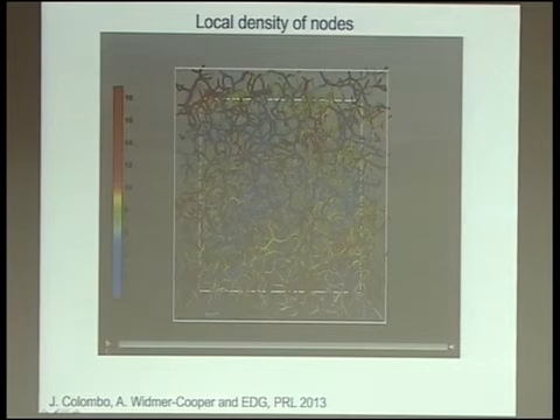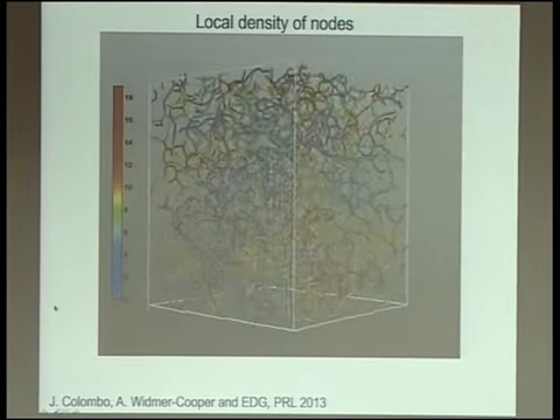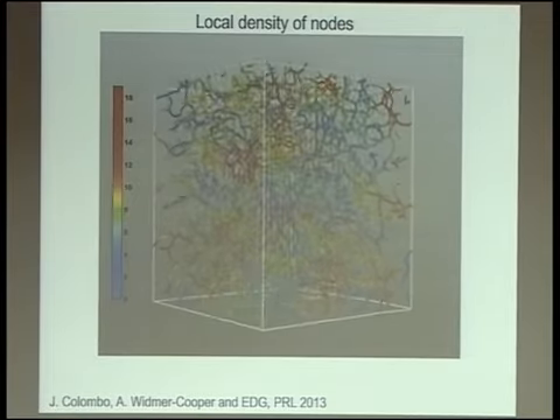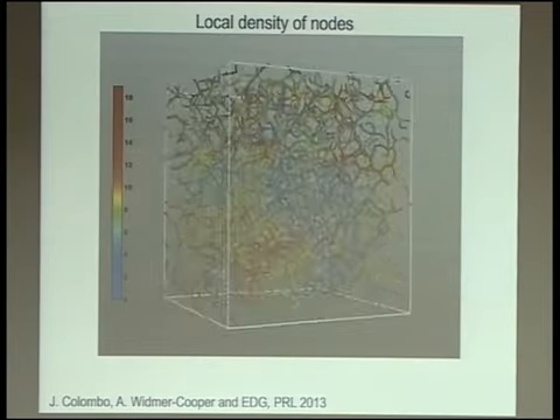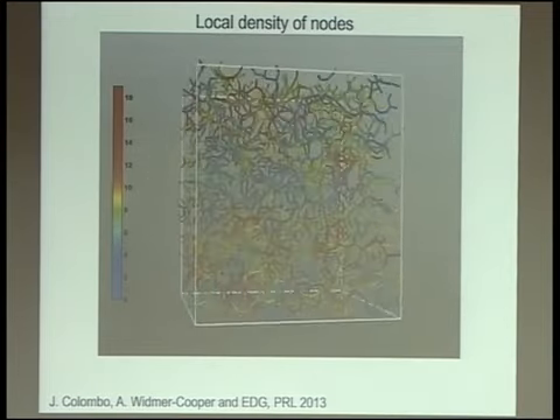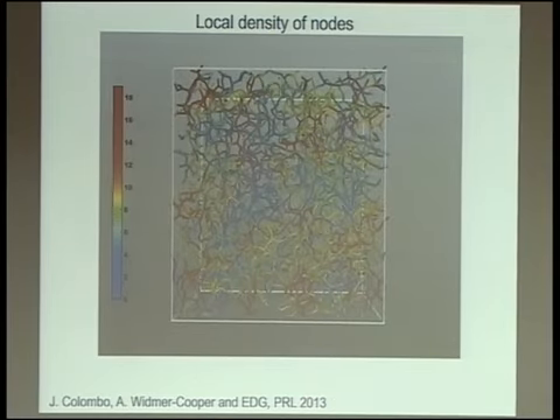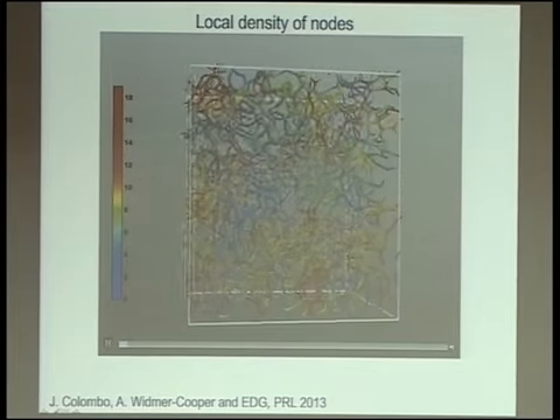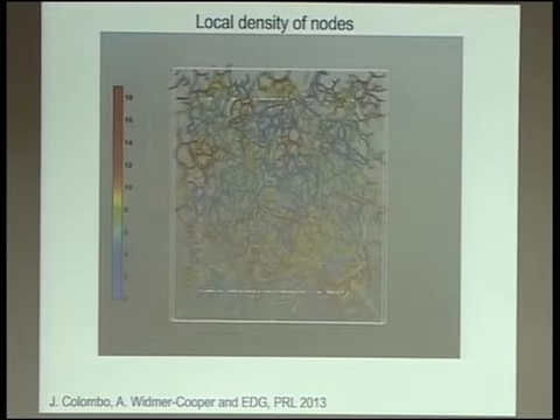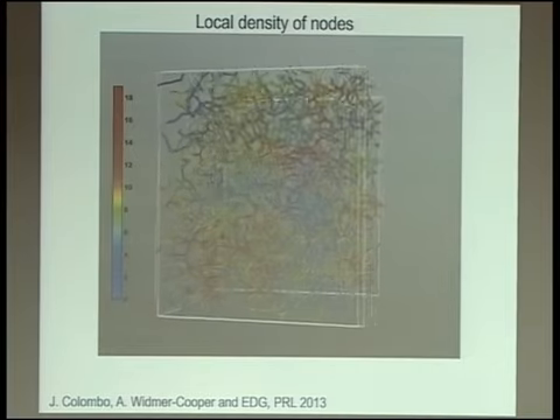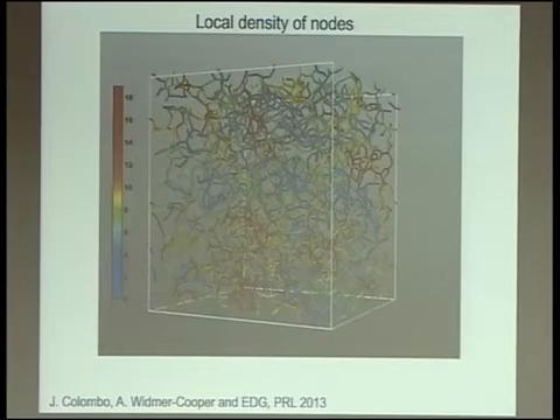So what it means is that we take a particle. Here I use this bonds representation just because it's easier to see things. And the color code is this local density of nodes that I was talking about. So I take a particle and I look at how many highly coordinated particles are around within a certain distance. So this is not the local coordination number of one particle, but it's really how densely connected is the environment around that particle. Okay, and so I am showing you first this type of spatial representation of the network, because you can see that it's very heterogeneous. So there are regions which are highly connected and regions like the blue ones which are very poorly connected.